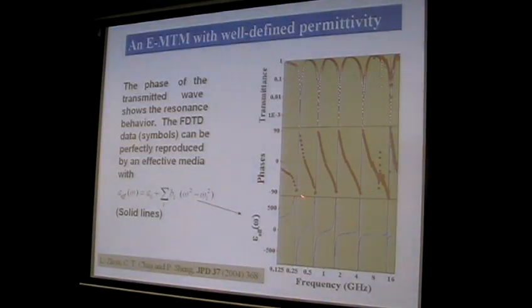This model gives a very good agreement with the brute force FDTD simulation. The brute force FDTD simulation is given by the dots, and the model result is given by the line. You can find a perfect agreement between these two. So at that time, we realized that this fractal plate is a very good quality electrical material with well-defined permittivity.